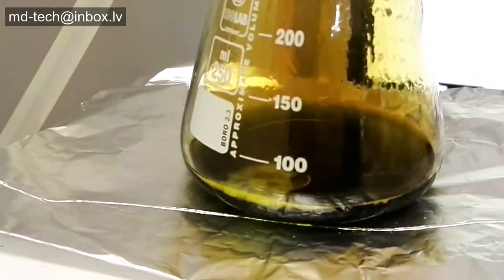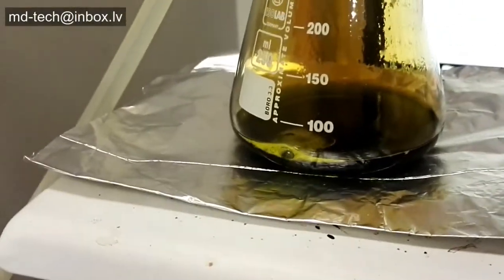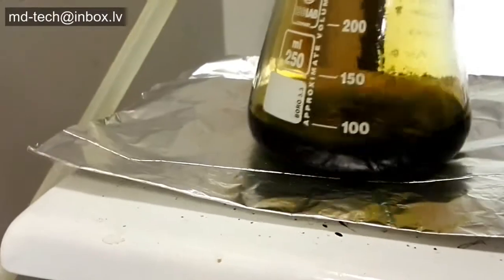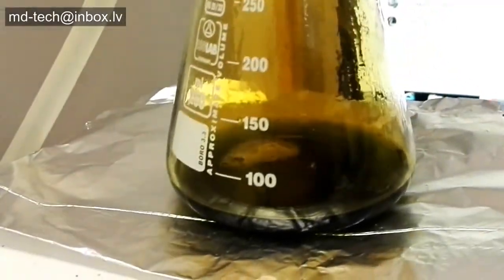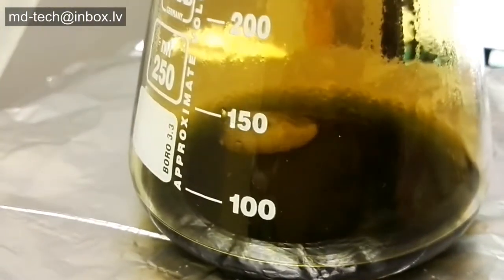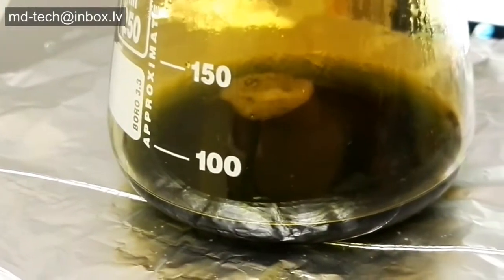The gold chloride and other metal chlorides in the aqua regia solution can now be separated from the undissolved material by filtering the aqua regia through a paper or glass filter. The material that was not dissolved by the aqua regia is filtered out, leaving a clean, clear solution of aqua regia containing gold chloride and other metal ions in solution.